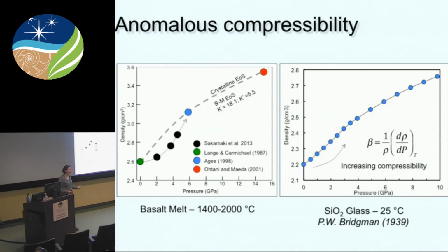Okay, at high pressure, it's been known for nearly a century. I mean, Bridgman did his original work in 1925 and then had to rebuild the machine and got slightly better measurements. And these measurements still hold for silica. We know that there's this region where we have increasing compressibility with increasing pressure. So normally, when you think about a material, as you increase pressure, you reduce the volume, and you compress the interatomic potential, so it becomes harder and harder to reduce the volume further. And that's what's shown here for basalt melts. This line goes through the sink-float data points, and it's what you would predict for crystalline equations of state.